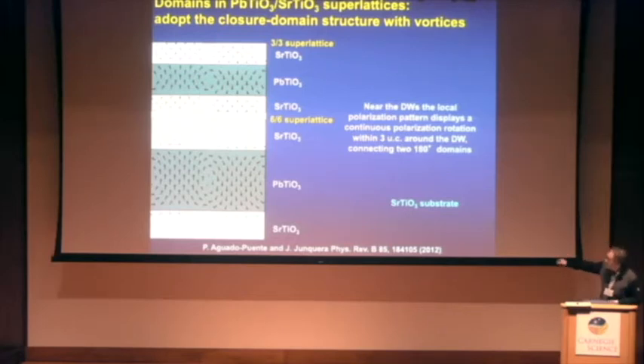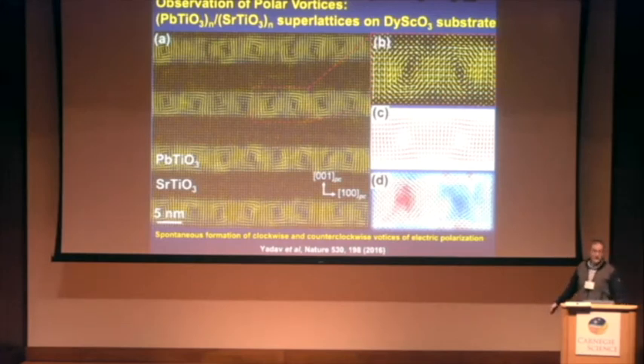So this rotational pattern has been recently detected experimentally in this very nice image obtained using aberration-corrected transmission electron microscopy by the group of Ramesh, where these so-called polar vortices are characterized here, as spontaneous formation of laterally alternating clockwise and counterclockwise vortices of electric polarization. So these vortices are, may be chiral, and that was one of the most important questions that we asked. So are they chiral and therefore optically active or not?